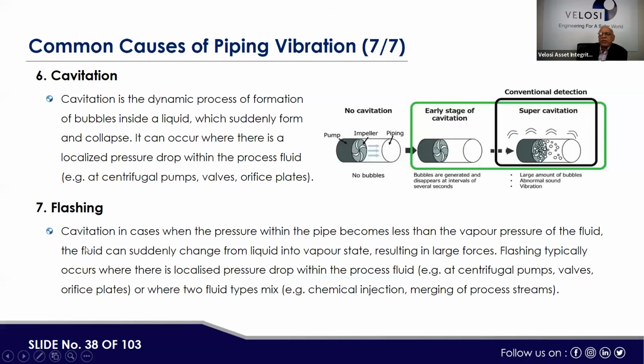Flashing. I earlier also mentioned flashing is a more common phenomenon in condensate, especially steam condensate, when it is being separated out, either by steam traps or some other reasons. Normally, if the high pressure steam condensate is separated, when it goes to the low pressure area or the deaerator area, in that scenario steam can flash and it can cause high erosion, corrosion, noise and vibration. So those areas are properly covered by appropriate design. Sudden pressure changes should be avoided, and so the flashing of the condensate back to steam could be avoided. And sometimes flashing is also a problem when we have chemical injections or merging of process streams which are in various phases.